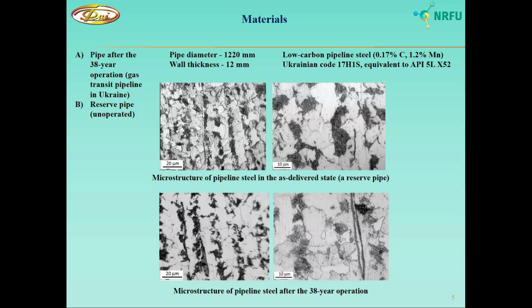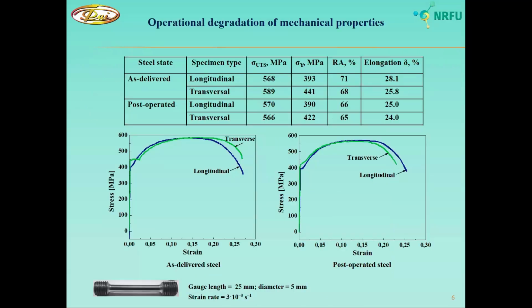Analyzing the microstructures of these steels, you can see that they are similar: bands of pearlite and ferrite, and also a significant number of non-metallic inclusions oriented in the rolling direction. Here we can see stress-strain curves for the studied steels, and also basic mechanical properties. And we can see that there is no significant difference in the strength properties. However, there are some differences in the plasticity characteristics.